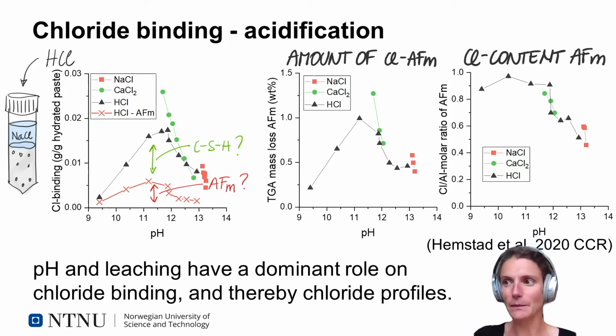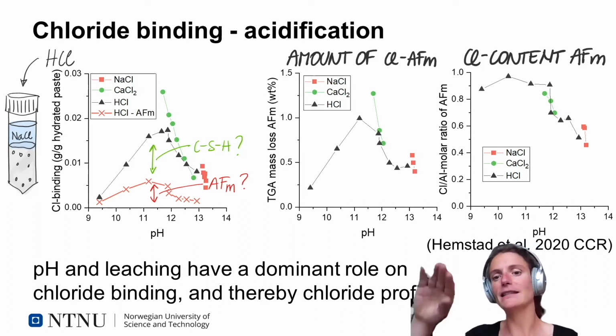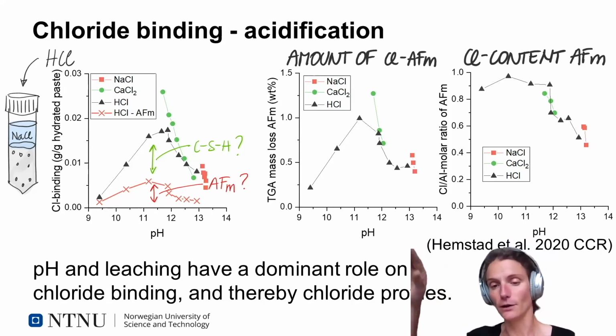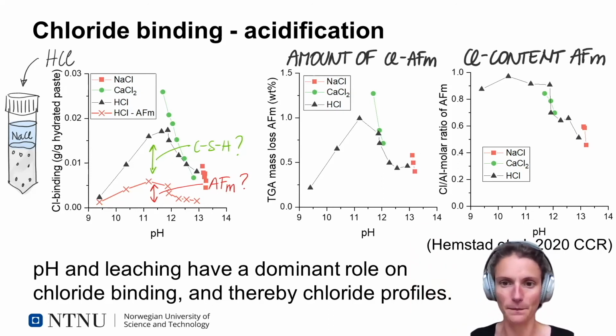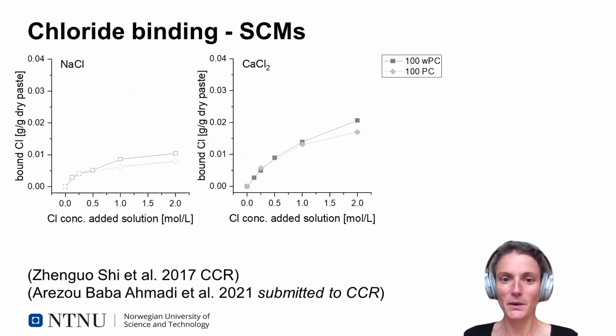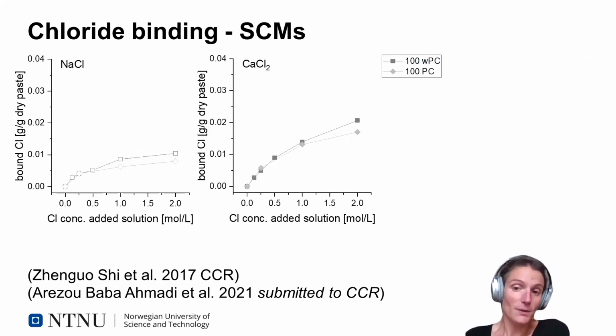This explains a little bit the peaking behavior we see in chloride profiles, where we see a lower chloride content at the surface and a slightly higher chloride content a bit deeper into the concrete. So highly relevant. So important is that all these results up to now were done on Portland cement. We haven't used an SCM yet.